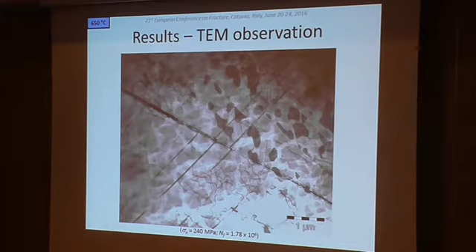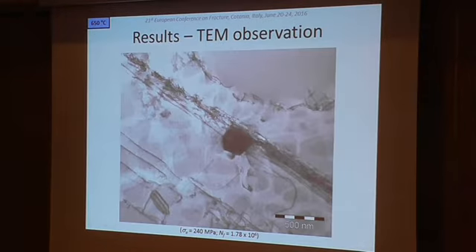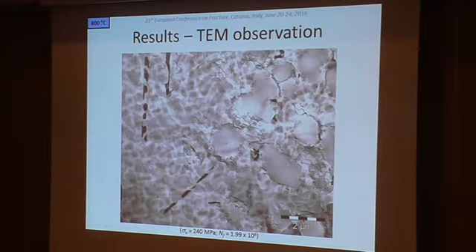Here are some pictures from conventionally prepared foils, where again they are showing the planar character of the dislocation structure at the temperature 650 centigrades, which goes well with the fractographic analysis that I showed at the beginning. This planar character is disappearing with increasing temperature. Here it was already not so pronounced. We had already dislocations in the structure of the material in channels and interfaces of precipitates.